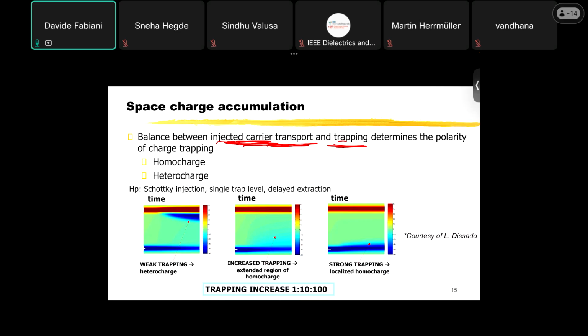Let me show you an example. This is a simulation that we did, simulating an injection following the Schottky law, one single trap level, and a delayed extraction at the opposite electrode. What you can see here is that if we have very weak trapping, which means very shallow traps, not very deep traps inside the material, the charge that is injected from the negative electrode can reach the positive one quite quickly,